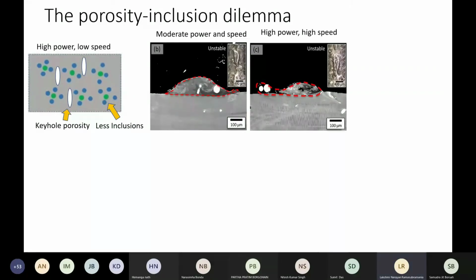Then we can also do, let's say, moderate power and speed. We saw that initially the melt track, or the single track of the melt pool, is terrible. It doesn't look very stable. It sort of forms something like a bead. And if we increase the power and speed further, the melt pool becomes even more messy.